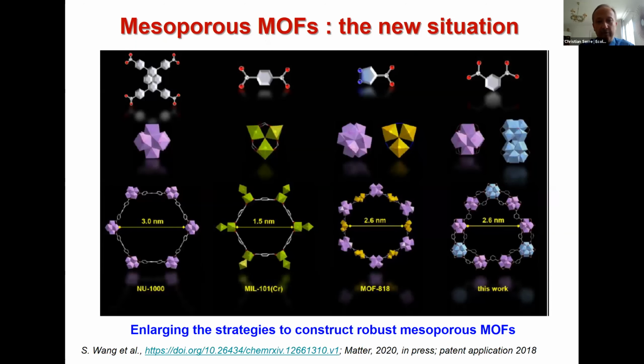So it's a good example of how we can tune the catalytic activity by playing on the ligand functionalization. So as a whole, if I come back to the comparison with the benchmark MOF, I think each of them has its own advantage. And here we bring an additional way by combining 2 different building units within the same MOF. It's particularly interesting in terms of stability because you keep the stability of the parent metal. And then also we have a lot of possibility of functionalization. So of course, we are lacking other examples to construct similar MOF based on 2 different homometallic building units, but I think others, based on the vast number of building units and ligands available, will probably develop a similar solid in the near future.